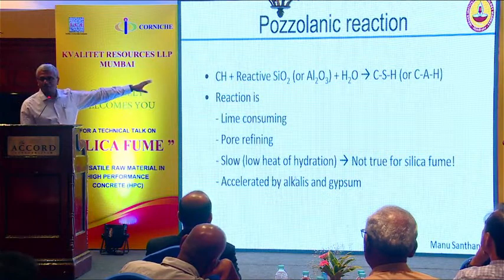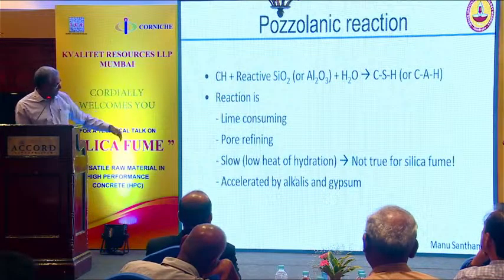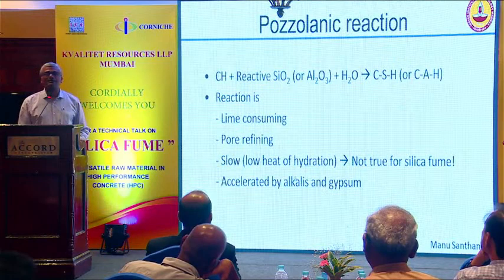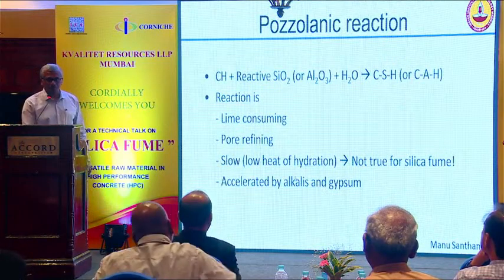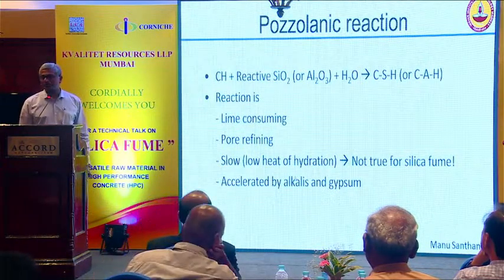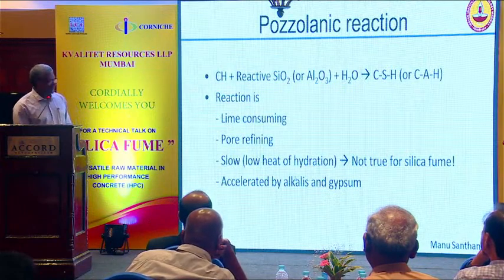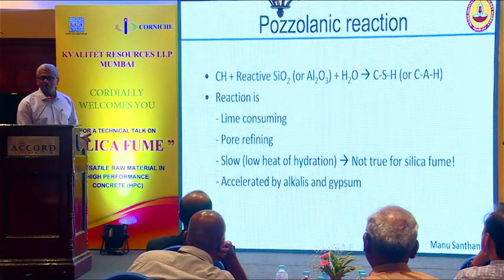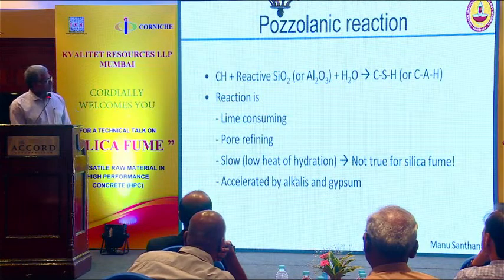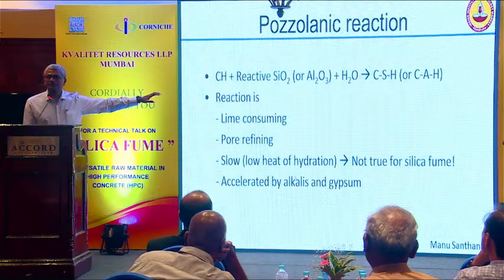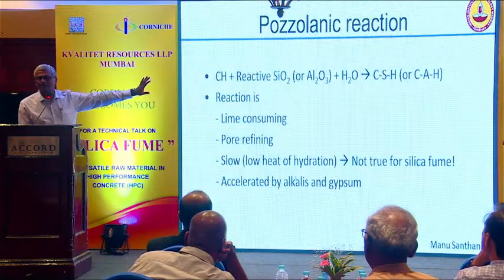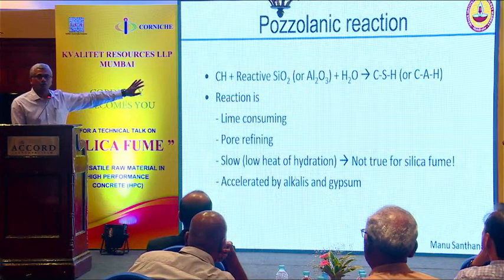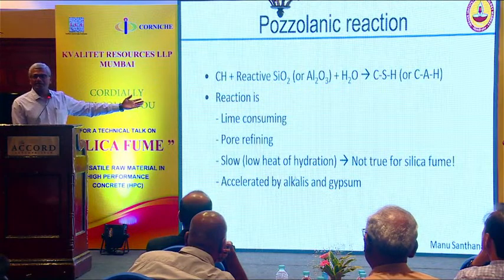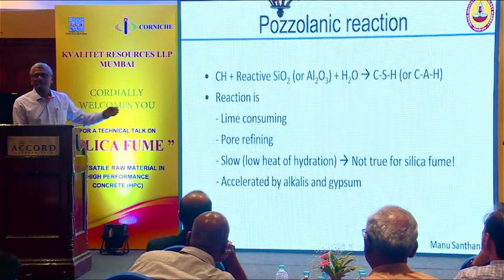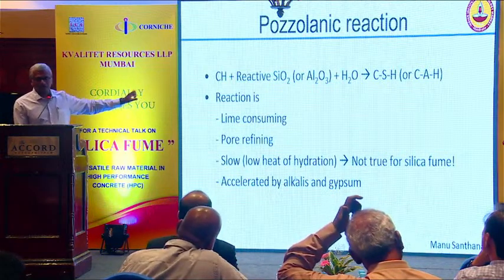This reaction obviously consumes lime, calcium hydroxide. It refines porosity, as I said earlier. CSH fills up pore spaces more efficiently than calcium hydroxide, right? So it fills up pore spaces, obviously that will lead to better durability, right? It's generally a slow reaction when you consider materials like fly ash or slag. Okay, slag is not really pozzolanic, so this reaction is not true for slag, but for fly ash or for some grades of calcined clay, this reaction is slow.